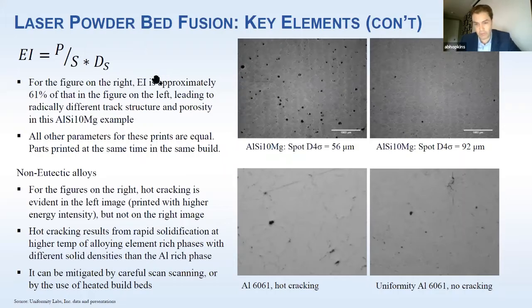But typically, you're on the order of about 60 to 80 joules per cubic millimeter printing today. Okay, and with special powders, maybe 20 to 30, 20 to 35. So non-eutectic alloys, I'll briefly mention aluminum 6061. I talked about this earlier in brief.